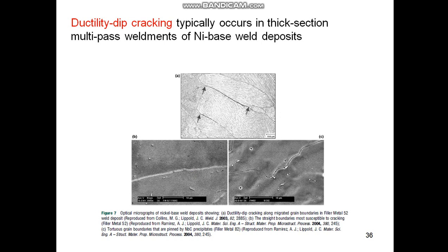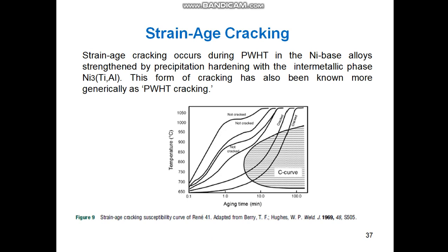Next is strain age cracking. The strain age cracking phenomenon is due to intermetallic phases of Ni3TiAl. This form of cracking is more generally known as PWHT cracking also. So you would see a temperature versus aging time in minutes. This is a C-curve, right? When you fall inside this curve, there is every possibility that you end up with cracking. But if you can bypass this C-curve, you are perhaps saved from the strain age cracking issue. So you have to manage your aging time in minutes so that you avoid this cracking.